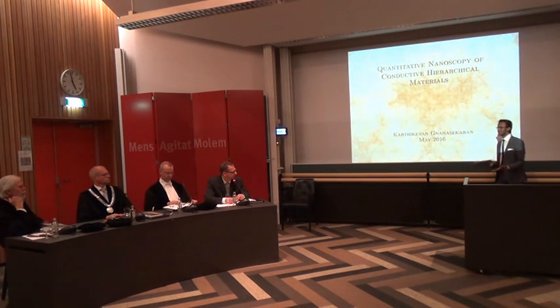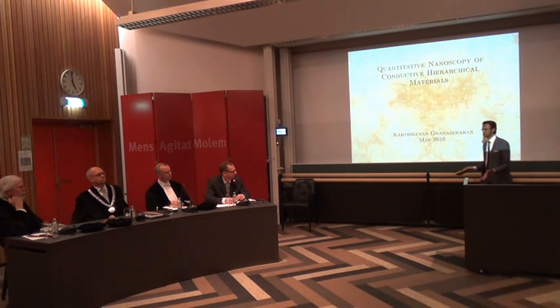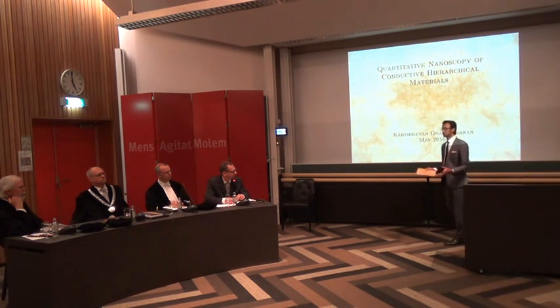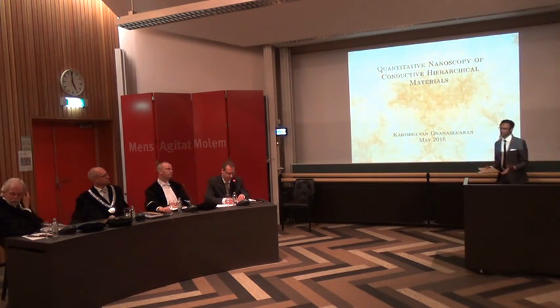how much percentage of crystallinity there is. Is that something relevant for the application? Well, yes, it is relevant for the application because at the end, this specific material is for gas permeability. Usually the gas transportation takes place in the amorphous phases of the tape. So, depending on the crystallinity and the material, you can tune that. With this technique, we can also measure the crystallinity and the crystalline orientation, whether they are flat-on oriented or edge-on oriented.